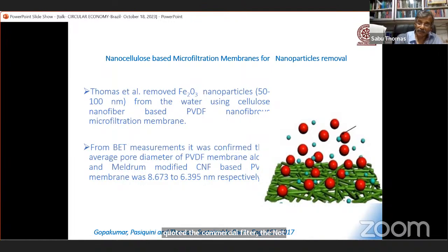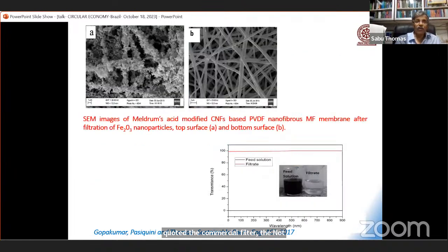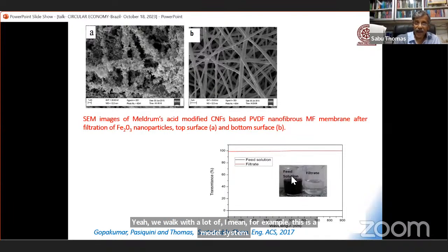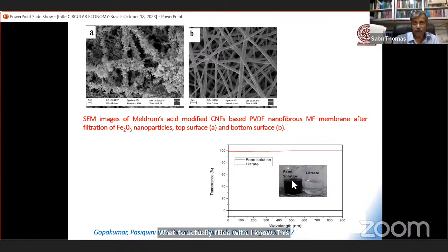Then we filtered water with a lot of particles. For example, this is a model system, water actually filled with iron oxide particles. So this is a model system, impure water. And if you look at the transmittance of this, it is almost zero because of the